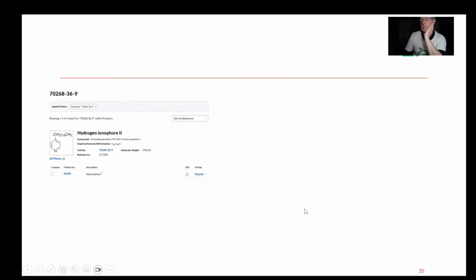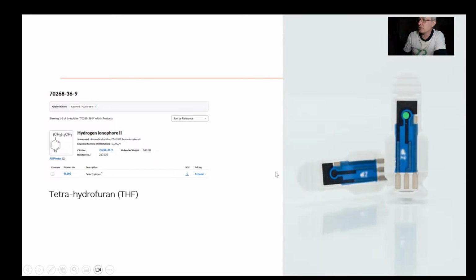And I think what happens is you take the ionophore of interest, you probably find that the papers say to dissolve it into THF, tetrahydrofuran, and then you essentially drop cast it onto hopefully a screen printed electrode. THF is quite volatile. It boils at about 60 degrees C, so do it in a fume hood. But it should evaporate quite quickly and leave you with the ionophore. I realise I've left out something here, which is you probably put it in PVC as well. You make a blend of the ionophore, PVC, polyvinyl chloride, and the THF, and that's what you drop cast, because then you're left with this kind of PVC with these ionophores embedded in it.